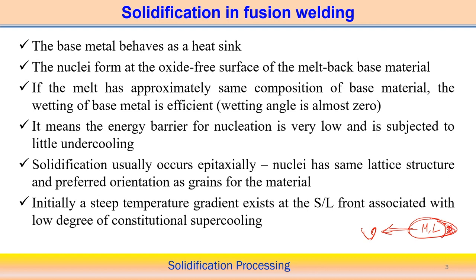Once moving, in the back part the nucleation will start, and then gradually the solidification starts here. Once the heat source moves away from this molten pool, solidification starts from the boundary, and at the center the solidification exactly ends at this particular position. In this zone the height, or maybe the span, of the mushy zone will be much more at the trailing edge of the welding process.